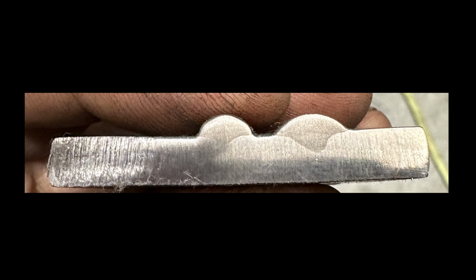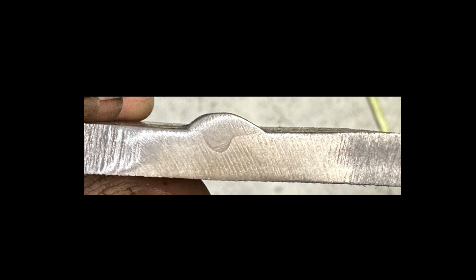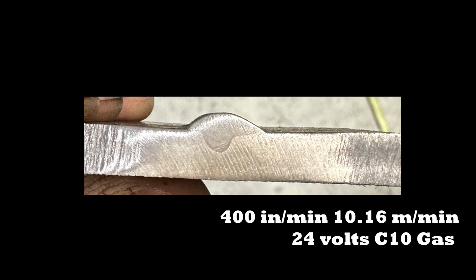So in the next picture, let's look at a spray arc weld. The settings I ran this at were a little bit on the low side. I ran a couple and then actually did the video. So this is probably the worst performing spray weld you're going to see in this video. But you can see really huge penetration in the middle of it. Not the best on the sides, but that's typical of what spray looks like in a flat position. It mainly punches in the middle.